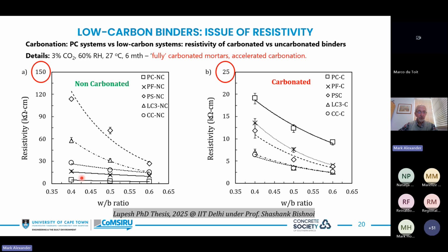And here you can see that the Portland cements or the plain cements are down at the bottom here, less than 20, often only 10 kiloohm centimeters. Hence, they're not very resistive, and therefore corrosion can occur. The other materials, this in particular here, this is a slag, PS there. It's an Indian material, really superb. And even the calcined clays are doing really well. Carbonate those materials in mortars at least, and under accelerated conditions, the whole picture turns around. Now the Portlands are doing much better. They've improved, plain cements, but the other materials have not. So the resistivity has come down, and you might say, well, does that threaten the long-term durability? Well, maybe or maybe not.